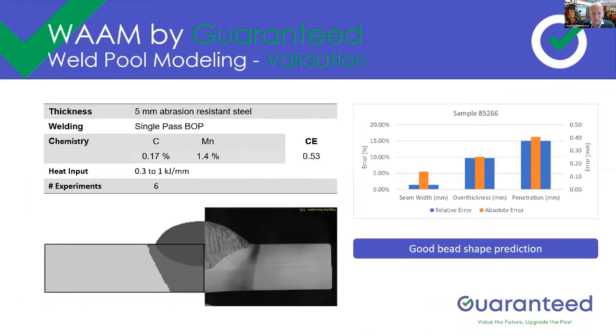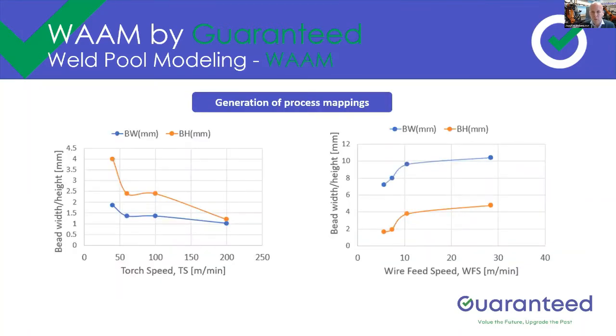A couple of examples on how we validated that. You see on the right-hand side of the picture the actual micrograph of the bead-on-plate test that we've done. On the left, you see the simulation results, and you directly see that they match very closely. This gives us confidence that we're capable of predicting the beads in the correct way. We're using that now to generate process maps, where, for instance, you see here that we're looking at the impact of variations in torch speed and wire feed speed on the bead width and the bead height, because these are essential parameters in order to ensure that we respect the right geometry of the part that needs to be printed.